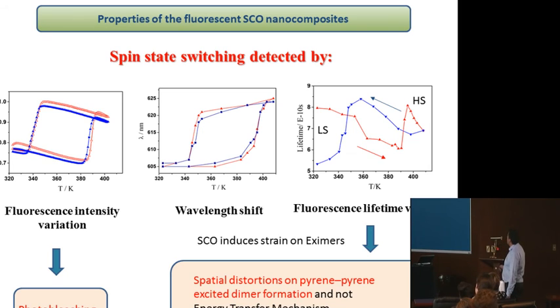Now, if you look at the fluorescence lifetimes, this is important to try to determine the mechanism involved in these modulations. It depends on the distance between the donor and the acceptor, between the spin crossover and the fluorescence part. If the two components are far, you normally have a reabsorption: emission of the photon and reabsorption by the complex. If you have the molecules close to each other, it's possible to have a FRET, a resonance transfer mechanism. So regarding the lifetime measurement as a function of temperature, it's possible to estimate the mechanism. In this case, you have a variation of the lifetime as a function of spin state. Normally when you have this kind of situation, this means that you have FRET, resonance transfer.